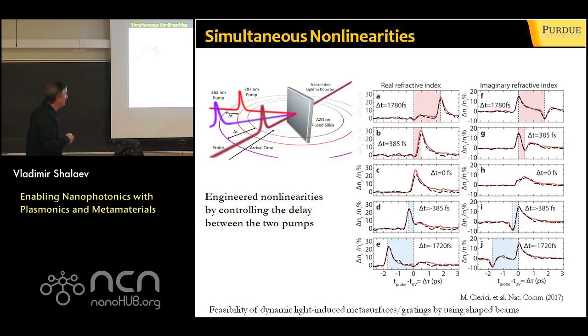What I'm showing here is the relative change in refractive index. And again, the change is a dramatic 30%, not like 0.01%, but like 30%. And depending on the delay between the two pumps, you could completely change the shape of this nonlinear response. And that's truly remarkable.